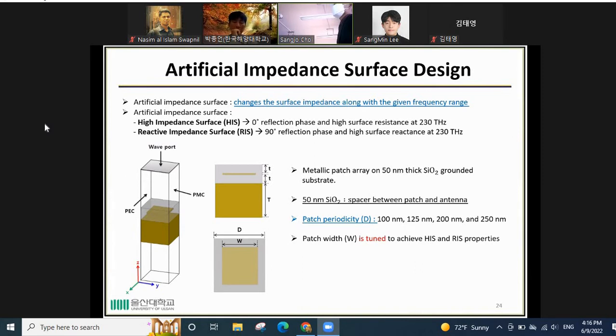We use a metallic patch array on a 50 nanometer thickness silicon dioxide substrate, and we put a spacer of 50 nanometer silicon dioxide between the antenna and the patch. Since we fix the antenna pitch size at 1 micrometer, we design the patch periodicity as 100 nanometer, 125, 200 nanometer, and 250 nanometer. Then the patch width W is tuned to achieve HIS and RIS properties.